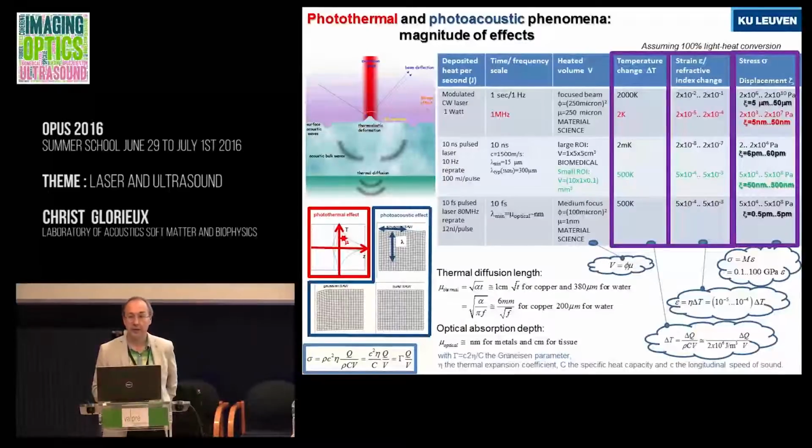And that's why you can use laser ablation. You can actually evaporate the material at the very top surface, and then the conservation of impulse will make that you also excite waves. But you can also do it more softly, just thermal expansion, which also gives stress and makes waves. In any case, temperature variations between millikelvin, if you don't have expensive, powerful lasers, and thousands of kelvins.